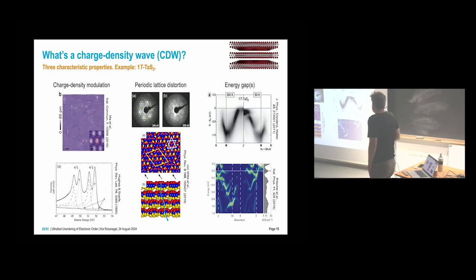And then the third signature, which is important when we want to use it as an electronic switch, is the energy gap. And also here, the gap structure can be very complicated. Gaps can appear at the Fermi level, but also at higher energies. So this means that in reality, charge density waves are not so simple as they may seem